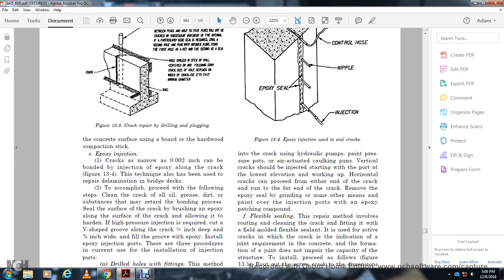The procedure: proceed with cleaning the crack of oil, grease and dirt. Seal the surface of the cracks by brushing epoxy along the surface of the crack, allowing it to harden. High pressure injection requires a V-shaped groove along the crack, about half an inch deep and 3/4 inch wide. Fill the groove with epoxy, and show the epoxy injection ports.